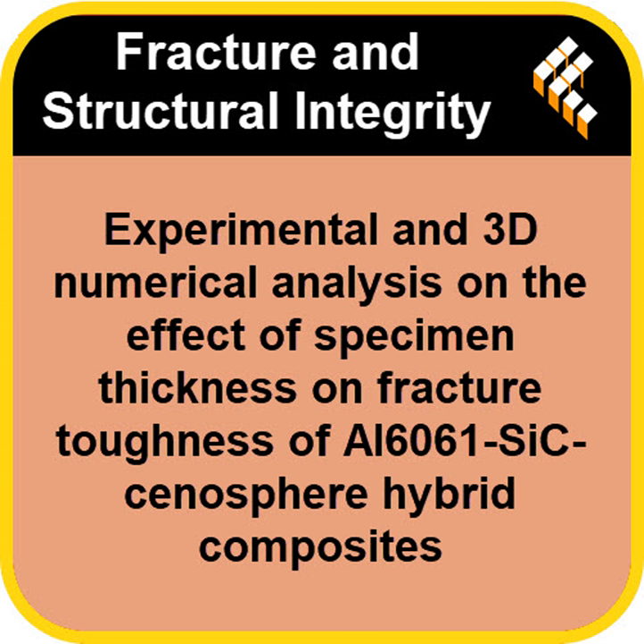Makes sense. Okay, so they had these 3 composite recipes. Now they needed to find that magic thickness threshold for reliable testing. How did they do the standardized tests? They followed the ASTM E399 standard very strictly. They used carefully machined samples called compact tension, or CT specimens, and they systematically varied the ratio of the specimen's thickness, which they call B, relative to its width, W. That's the B/W ratio. They tested it across a range from 0.2, quite thin, up to 0.7, which is pretty chunky. And the test itself involves making a tiny crack and then pulling the sample apart.